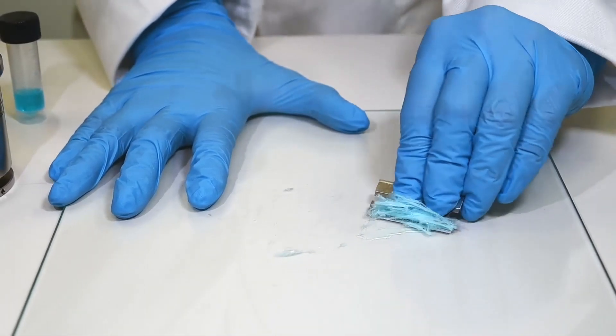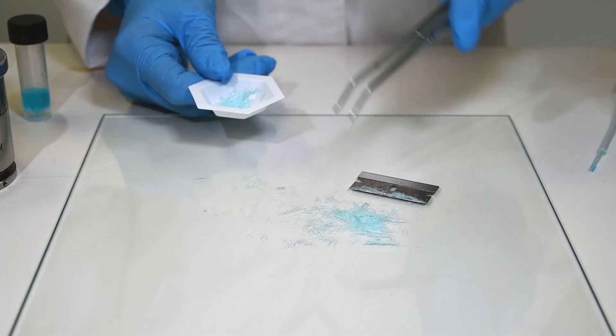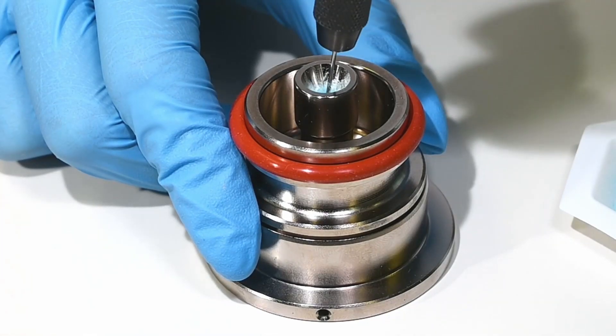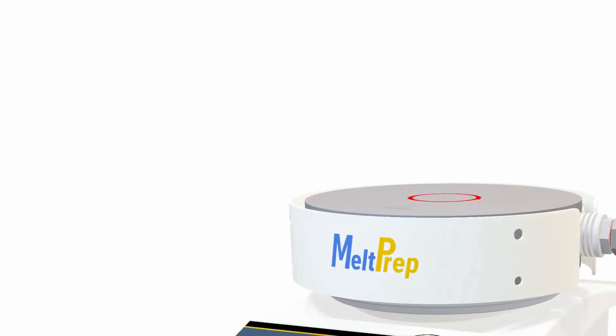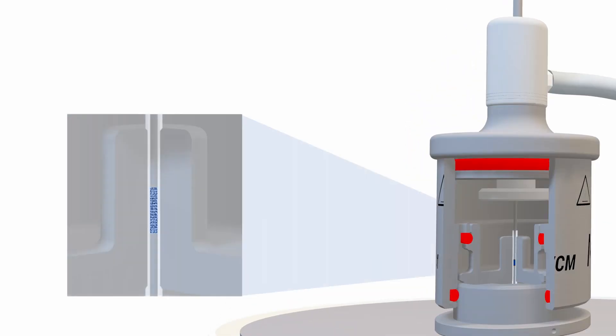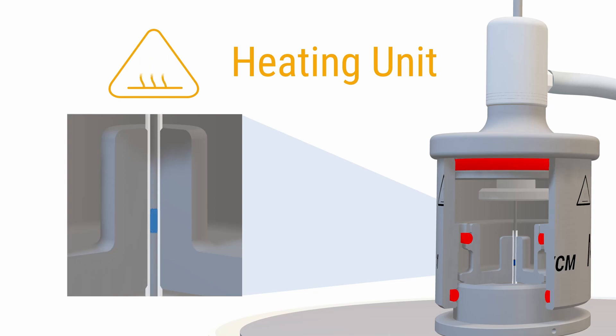Fusion-based ASDs as we obtain via VCM are more stable. Select the residuals and load them into the VCM tool. Assemble the chamber with the main body and lid. Run the VCM process. The vacuum removes the residual solvents and subsequent heating will initiate melting. A homogeneous melt is obtained within minutes.